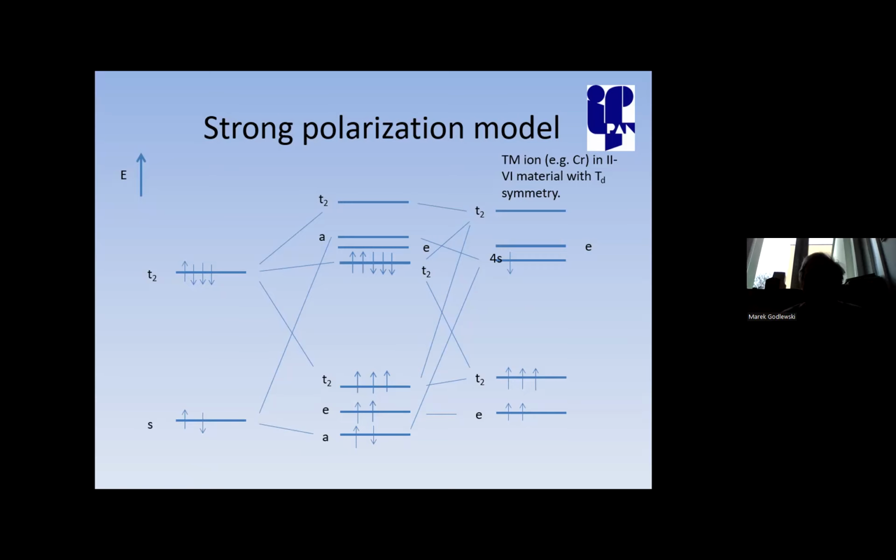So we no longer have pure d-like states. It means that the rules we stated for transitions between the valence band, transition metal ions, and conduction band in case of photoionization should be characterized by quite different selection rules. It's no longer true because we never have pure d-like functions now. They are always mixed with p functions of the ligand, and p-d transition is parity allowed.